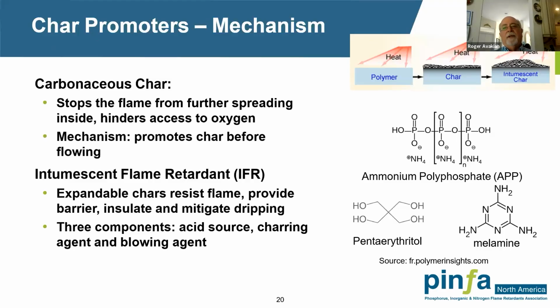Again, char formers. This is a typical intumescent type of mechanism we'll talk about here, typically making a carbonaceous char. So you'll see later on, we'll talk about a non-carbonaceous char. But in this case, we're going to form a char that's primarily made from carbon. You can see the little schematic in the upper right-hand corner. When you heat a polymer, you can form a char, which many times will happen, similar to burnt sugar. But you can also form an intumescent char, and that's typically a char that has a foam type of structure.